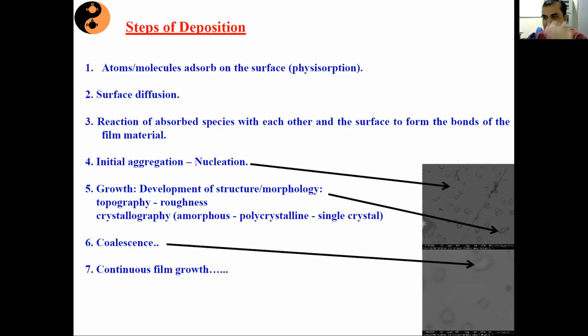Okay, similarly, these evaporants, when they reach the substrate surface, they first try to attain a thermal equilibrium. They get adsorbed on the substrate surface. After attaining a thermal equilibrium, they hop onto the substrate surface from one side to another side, unless and until they find the second, then third, then fourth, then fifth, and that is how this nucleation actually takes place. And when this nucleation takes place, only then some structure is actually formed.